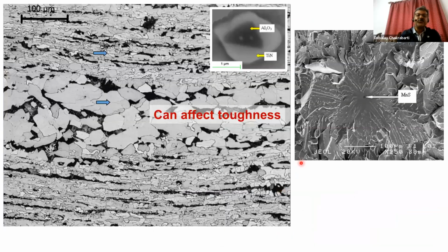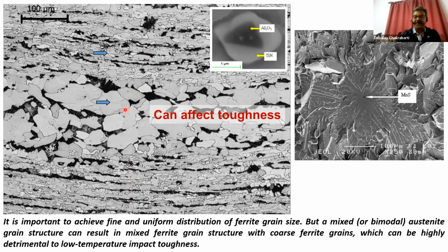So let me just quickly show you a few images. This is what is called grain size variation. You can see very, very coarse grain in between very fine grains. So these coarse grains, when associated with coarse precipitates, can be seriously detrimental to the toughness. This kind of microstructure often arises in niobium microalloyed steel, which we want to avoid. And as I said, we need a very fine and uniform grain size distribution.